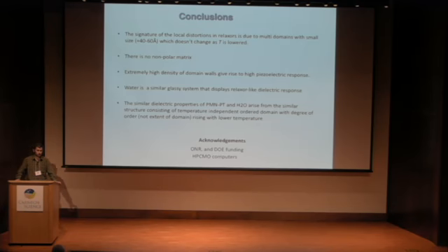So we think it has to do with this multi-domain structure. I didn't show this before, but we tried to model it with simple models where we have, let's say, 180-degree domain walls or 90-degree domain walls or no domain walls, and nothing really fits except when you have this kind of, we did 71-degree domain walls. Maybe other ones will work also, but the message that we got, and again, this is an area that we have to do a little bit more work on, is that you have to have a multi-domain state of a certain kind of domain wall orientation to get this diffuse scattering butterfly shape. Otherwise, you will not get it.